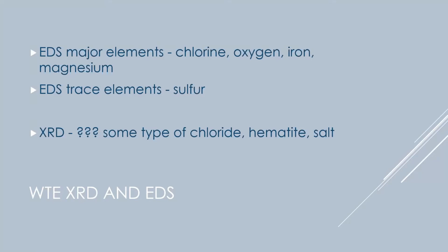I don't think we have to go over this one. Of course, you can see how this is really old results, because back when I did this, we didn't have quantitative energy dispersive spectroscopy. We just had to compare the heights, and that's all there was. As you can see, in waste to energy incinerators, the bad actor is chlorine. We get very little sulfur. It's kind of the opposite of a coal-fired boiler. And for the majority of it, we couldn't determine what it was because in the atlas of X-ray diffractions, there was nothing to identify what was there. That's just the way it was back then when we first started looking at these.